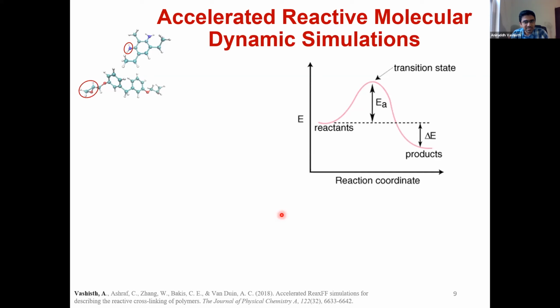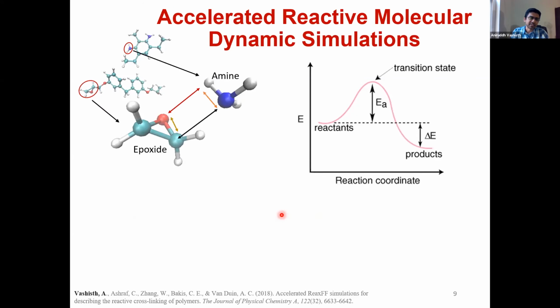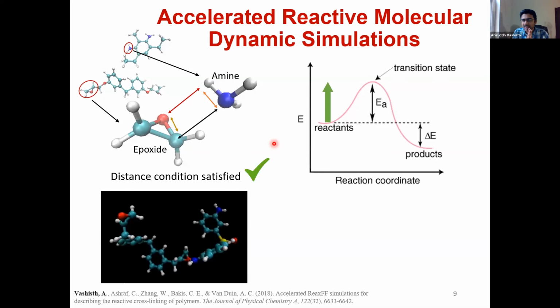Well, the cutoff method is not exactly what's happening in your reactions. I mean, there are a bunch of different things that contribute to a reaction. So what we did, we came up with this method that we call the accelerated reactive method. So let's just consider the reactive sites, just the epoxide and the amine. We agree that the first condition has to be similar to what people prior to us have done. We say that once these molecules' reactive sites are within a certain distance from each other, that's criteria number one satisfied. Once this is done, what we do is that we provide these reactive sites with enough energy that they can go up to a transition state. And this energy that we provide the reactive sites is usually equal to the activation energy for that reaction. Then it's completely up to the reactants if they want to react or not.